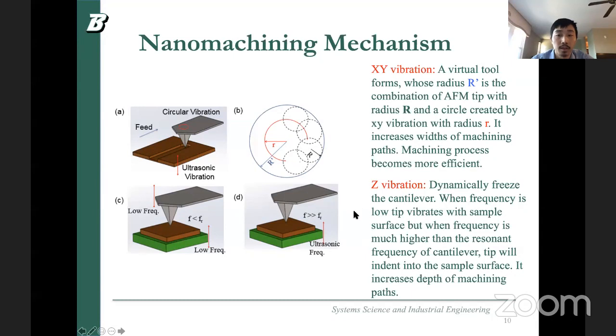For the Z vibration, the function is to dynamically freeze the cantilever, so the cantilever can be easily indented into the surface. As we know, if the substrate vibration has a very low frequency, the AFM tip will vibrate along with the Z vibration, so the tip will not easily indent into the surface, and it's not easy to generate patterns. Because of the ultrasonic vibration frequency, the AFM tip is not able to move or vibrate along with the Z vibration. Therefore, the AFM tip can indent into the sample surface, so that can easily generate different depths of nanostructures.